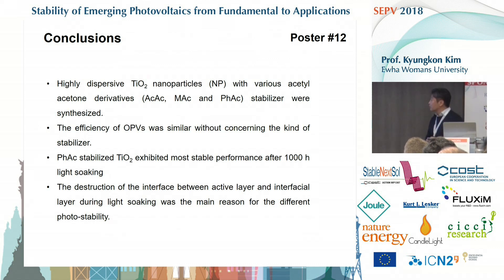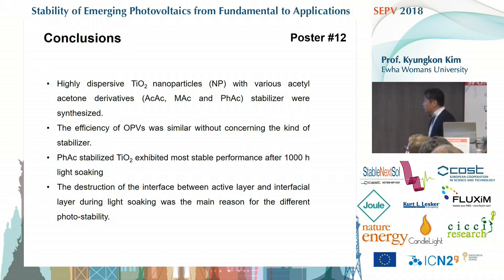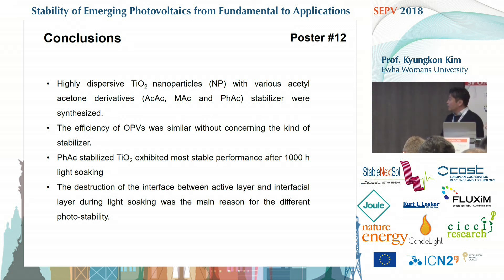I want to conclude my talk. We prepared three different types of nanoparticles and found that the phenyl-acac stabilized nanoparticles exhibit the most stable performance. This is due to the destruction of the interface between the active layer and interfacial layer in other stabilizer cases. I especially want to thank my student. Thank you very much.